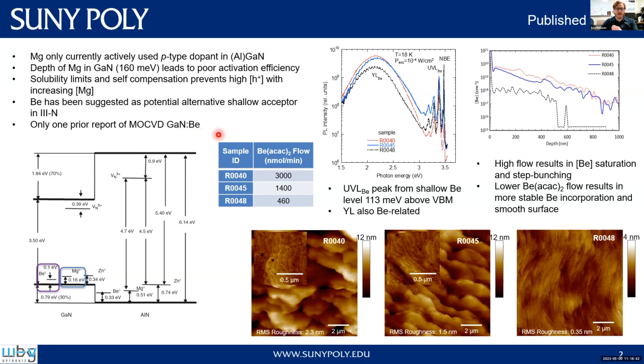So to that end, we grew, using MOCVD, beryllium-doped GaN using a variety of conditions. Specifically here, we have a selection of beryllium acetylacetonate flows. That's the beryllium precursor. As you can see in this PL plot, we found that all of the material showed a UVL band at 3.38 eV, which is indicative of a shallow beryllium acceptor level 113 meV above the GaN valence band max, which is shallower than any other acceptor level.